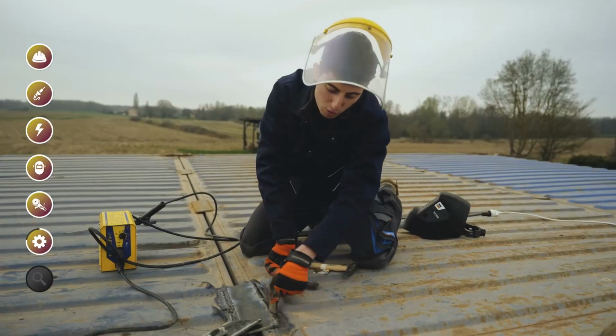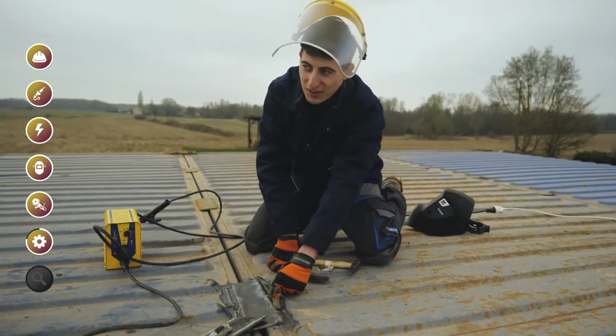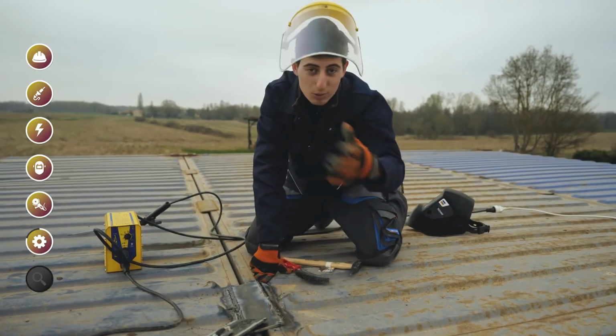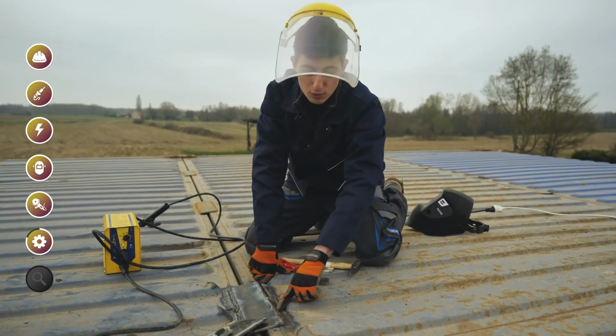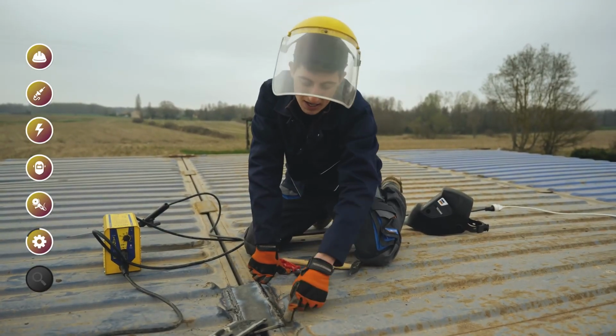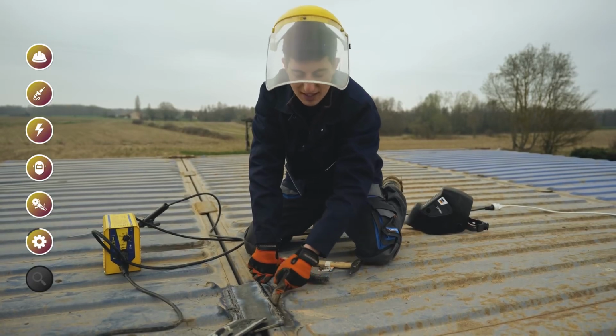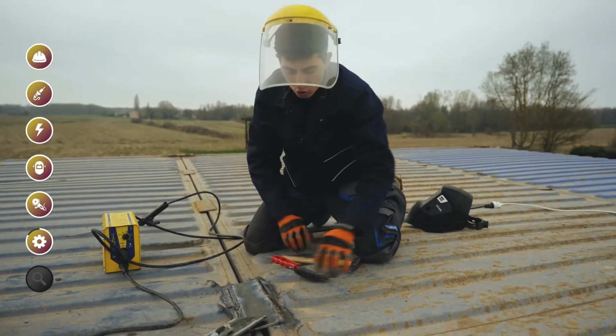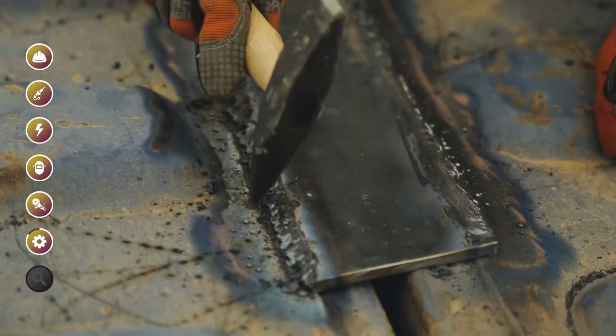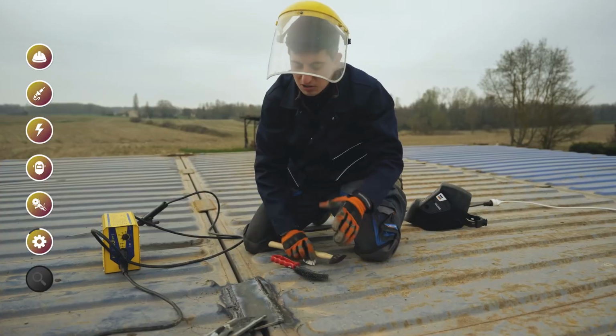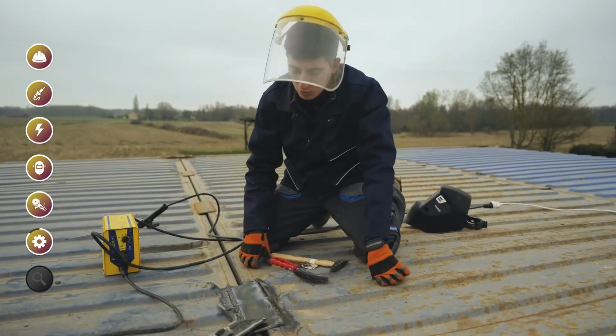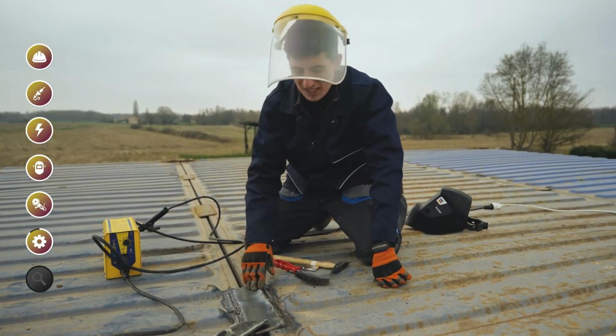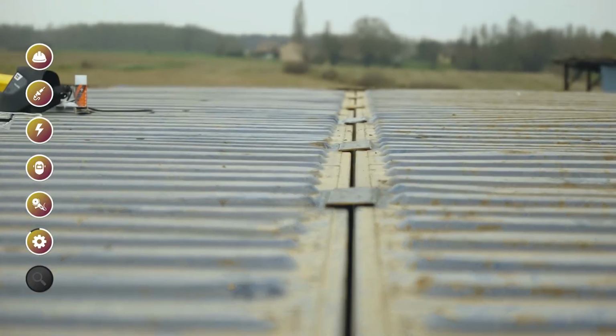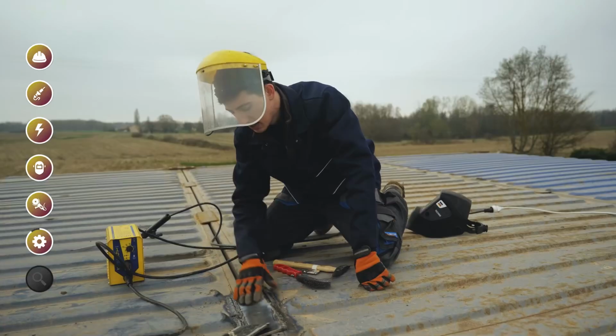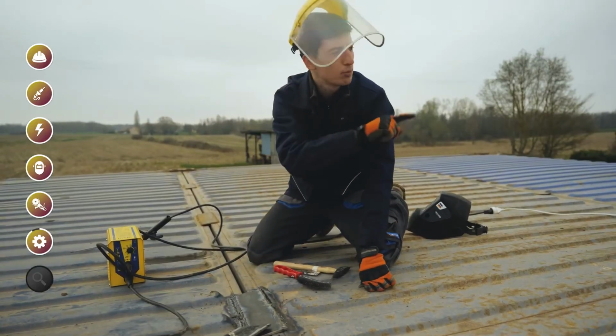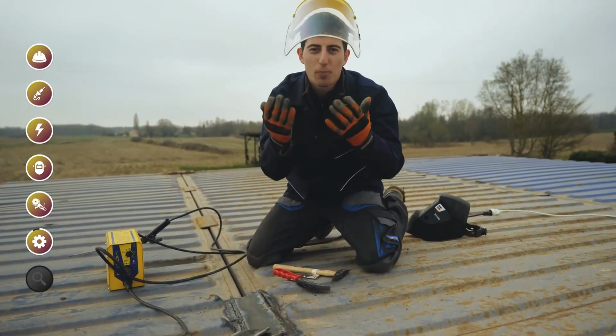Well, you see, the welding job is messy because I haven't welded in several weeks and I need some time to get back in shape. It's not pretty, with holes still clearly visible. Where I removed the slag, and where the slag remains, is that little black layer that I can remove quite easily. It depends on the spots. But these plates are tricky because they're a bit slanted, so the welding is quite complex. But I'll show you other plates that I did much better so you can compare.